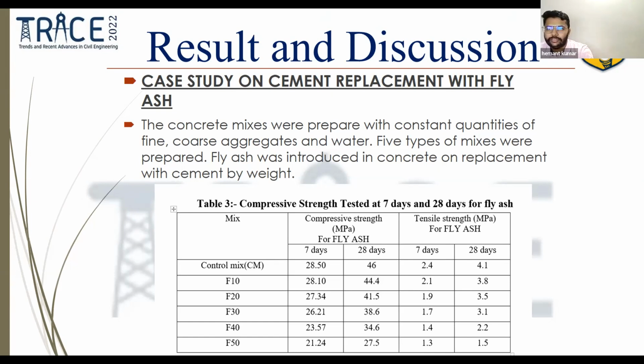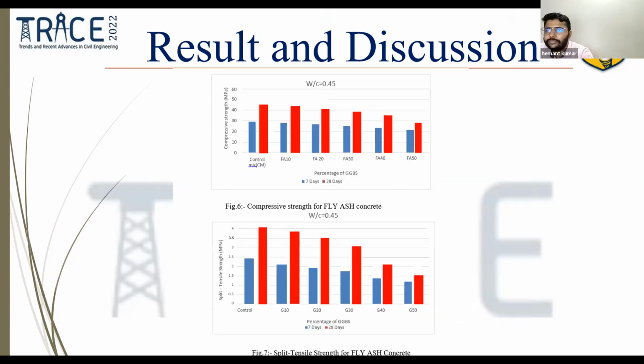And we get this compressive and tensile strength for 7 and 28 days. These are the charts showing the result. In this, we see that by adding fly ash, we do not get high tensile and compressive strength. Our strength goes on decreasing as we increase the percentage of fly ash. But it will increase the workability of concrete.